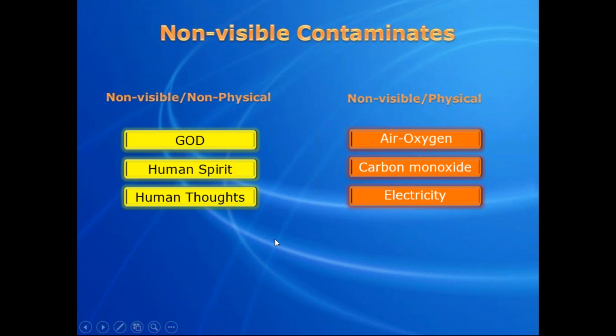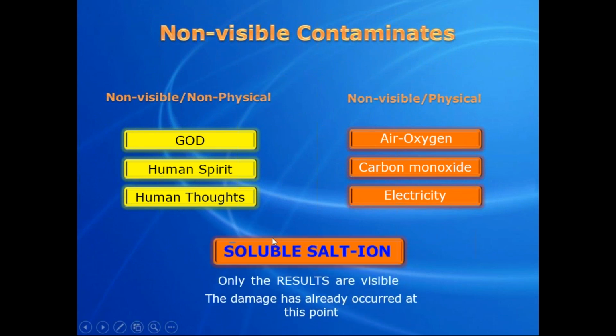Here's an example of some of the non-visible things we talk about, as we're always talking about these salts are not visible. Well, people that see table salt say, wait a minute, I can see that, but not when it gets wet and starts dissolving and goes down into the micropores of the steel. When you do start seeing those effects is when the micropores of the steel become inundated with the salt contamination and the moisture, and it starts turning brown, black, or what have you, and you'll start seeing it that way.